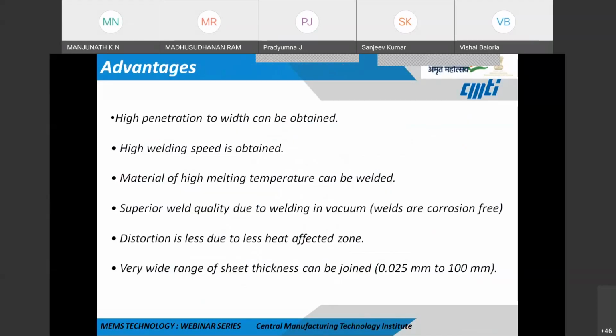Coming to the advantages of e-beam welding, high penetration can be obtained, and high welding speed is obtained here, and materials of high melting temperatures can be welded. Like when I talked about tungsten, they can also be welded. And there is superior weld quality due to welding in vacuum; these welds are usually corrosion free. And distortion is less due to the less heat affected zone. As I showed in the previous slide, the heat affected zone is very small, so hence there is less distortion in the material or the grain structures of this material. And a very wide range of materials thickness can be joined, starting from 0.025 mm